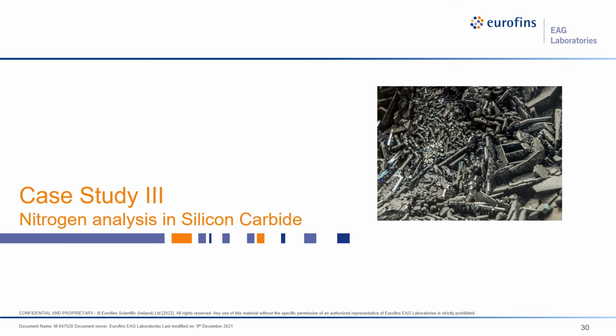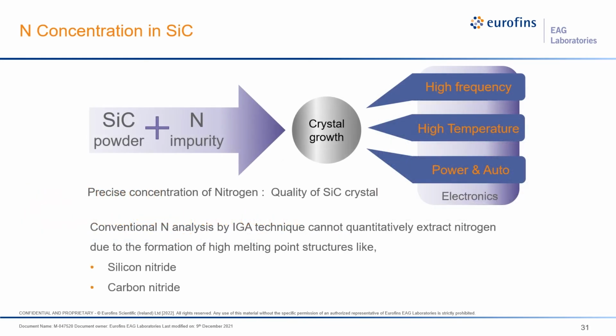This case study is about nitrogen analysis in silicon carbide sample. To optimize the clear extraction of nitrogen, nickel capsule and niobium flux are used. Let's see in details. Nitrogen often serves as a donor in silicon carbide crystals that are used in high frequency, high temperature, power, and auto electronics. Precise doping of nitrogen is necessary to manufacture various quality of silicon carbide crystals. However, conventional IGA method for nitrogen analysis cannot be used since at high temperature, melting silicon carbide with nitrogen will produce silicon nitride and carbon nitride, resulting in improper nitrogen extraction.